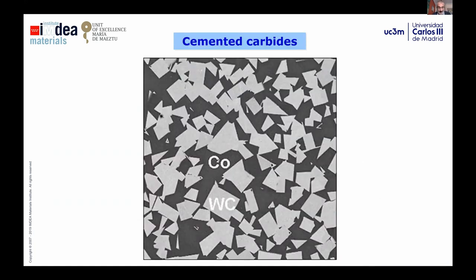It's the cemented carbides. In this microstructure that we have on the screen, you can see a matrix of cobalt with a reinforcement of tungsten carbide. And we have this specific microstructure. And with this specific microstructure, we have some specific properties that allow this material to have the main part in the market for the cutting materials in the world. That means that no other metallurgy can produce this specific microstructure.